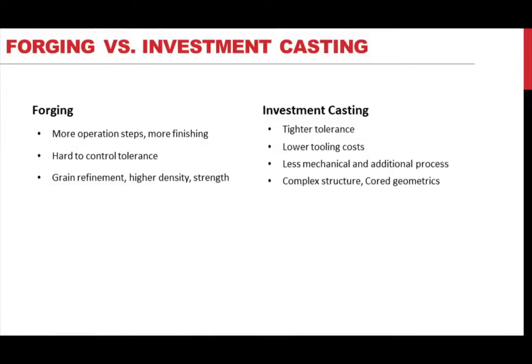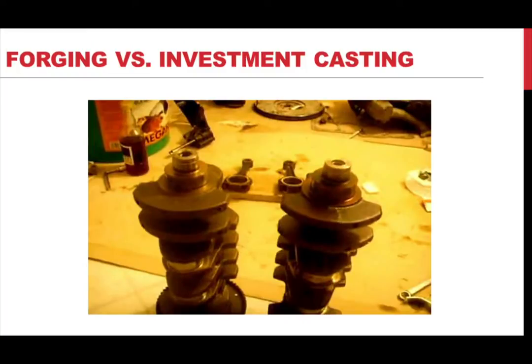Among the same class of manufacturing processes, the forging process has many advantages as well as trade-offs. For our part, the crankshaft can also be made by using investment casting. Those two can use similar materials to produce similar parts. Comparing those two, forging requires more operating steps as well as the finishing step because of the low tolerance, while the casting could result in higher tolerance for the requirements. Another aspect of those two processes is that although they can use similar material and produce similar parts, the result in the quality of the part is different. So here you can listen to the difference between the same products.